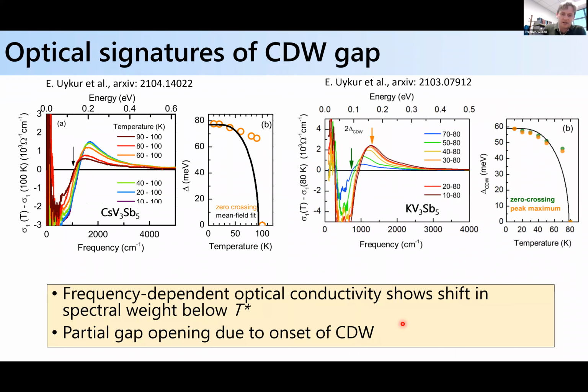And then our collaboration with E. Uykur has also looked at optical signatures of the system. So basically looking above and below this T star transition, starting with the cesium system, they can look at the frequency dependent optical conductivity and look at the difference above and below. And what they find is that they see spectral weight pushed up, consistent with an electronic gap opening. They can fit the onset of this gap, and the optical gap from their analysis is almost 80 millielectron volts.